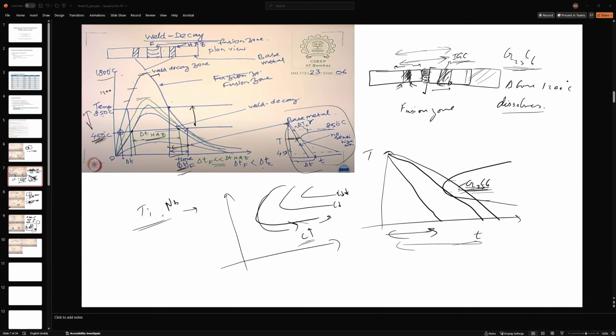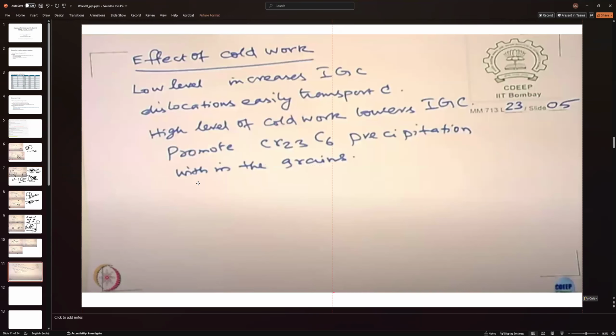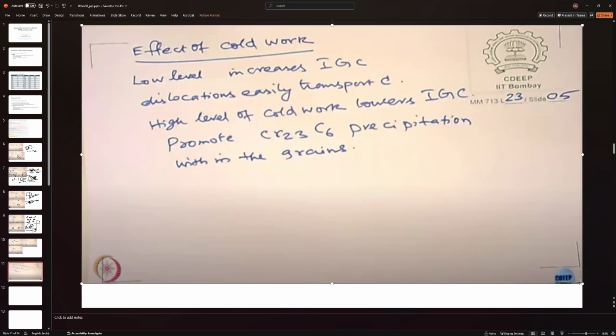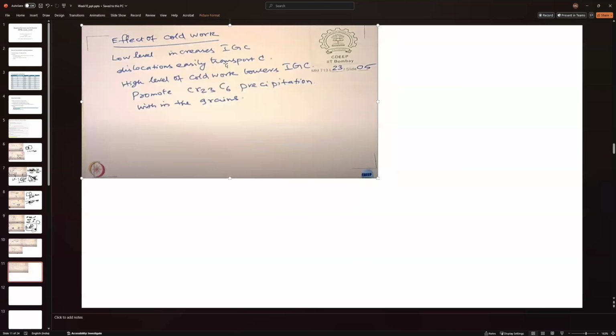Type of surface treatment. Effect of cold work. So low level cold work increases IGC. Dislocations can easily transport carbon. And if you have high level cold work, that actually reduces IGC, because it promotes your chromium carbide precipitation inside your grain instead of the grain boundary.